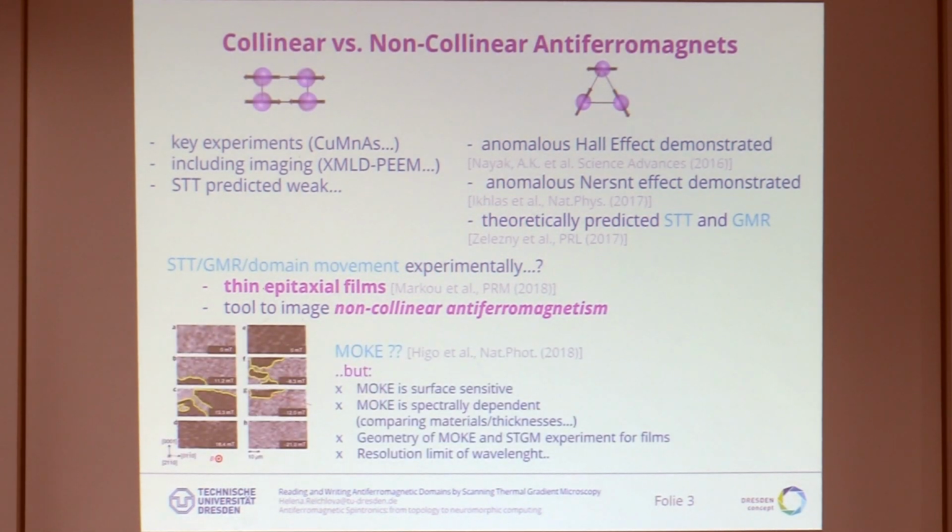So magnetic force microscopy probably will not work. XMLD-PEEM I also didn't see working. There is a very nice report of the magneto-optical Kerr effect, but the magneto-optical Kerr effect for our application has several strong disadvantages. One of them is that it's surface sensitive. We very much like to put something on top of our film, some capping, sometimes metallic. So all these interfaces are causing some interference, making the MOKE a little bit uneasy.